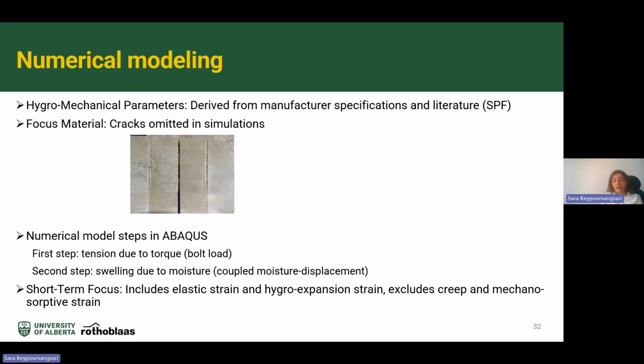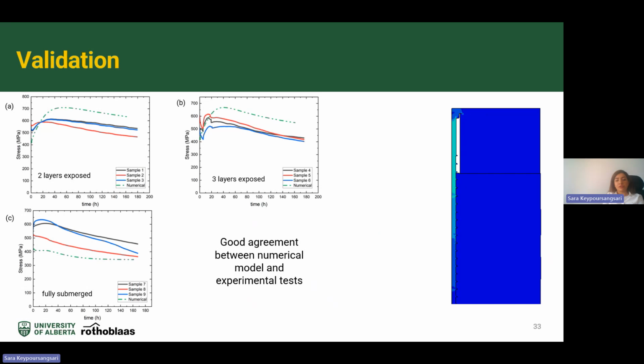We opened most of our samples, and we couldn't find any severe damage, severe crack, or withdrawal. That's why in our simulation, we didn't consider the effect of withdrawal failure or any kind of crack. As I mentioned, we use a two-step numerical model in the Abaqus software. And we consider the effect of the torque and the effect of the moisture content change in the short-term condition, because we only exposed our samples to water for only 1 week. So we didn't consider the effect of creep and mechanosorptive strain. And here you can see the results. The green dashed line shows the result from the numerical analysis. This is the axial stress in self-tapping screws caused by torque and moisture content change.